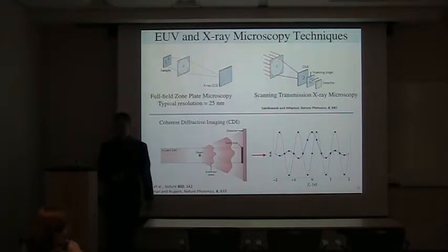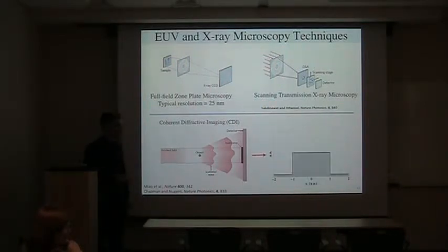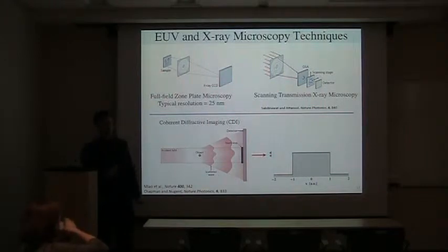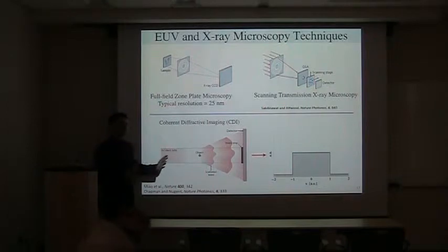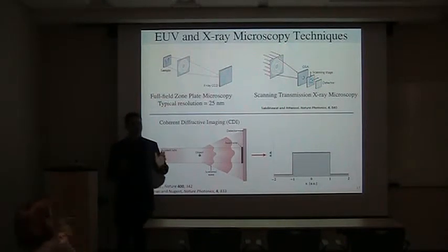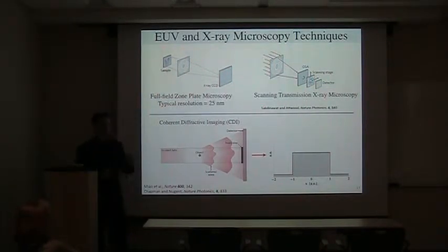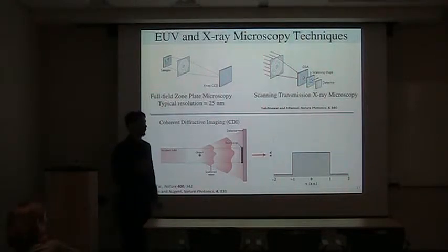And if we look back one step further to the object, we can see that the object is now surrounded by zeros. We work backwards in the microscope, where we insist that the object is surrounded by zeros, which allows us to Nyquist sample the diffraction intensity. And in this way, we can now get an image of the diffracting object using coherent X-rays and bypass the need to use this aberrated, very lossy Fresnel zone plate. Okay? It turns out that Fresnel zone plates are quite lossy. You're going to get about 3% of the light through this.